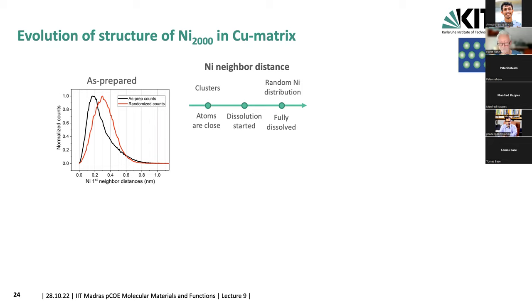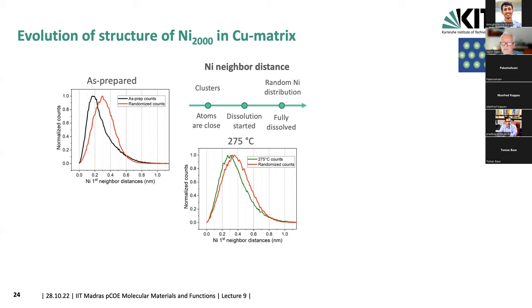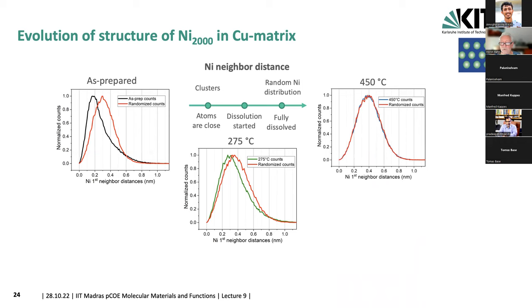Now, if you anneal the sample at 275 degrees Celsius, some intermediate temperature, of course, nickel and copper start to interdiffuse. And now what you see is that the green curve is the measured nickel-nickel pair distribution, and it becomes already closer to the randomized count, which is identical to the other curve on the left figure. And then if you go to higher and higher temperature at 450 degrees, each time annealed for 2 hours, you see that the blue curve basically overlaps with the red curve, which means we have a solid solution of nickel in copper.